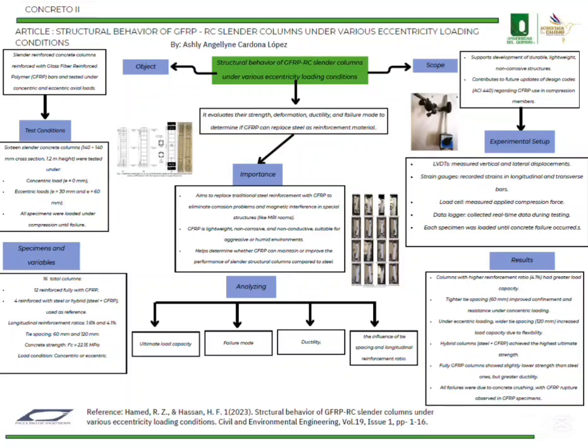GFRP is a composite material made of glass fibers embedded in a polymer matrix. It has several remarkable characteristics. It is much lighter than steel. Its density is only about one fourth or one fifth of steel's. It has a high tensile strength, sometimes even comparable or higher than steel. It is corrosion resistant, making it ideal for aggressive or marine environments. It is non-conductive and non-magnetic, which makes it suitable for electromagnetic sensitive areas. However, one limitation is a lower modulus of elasticity, meaning it deforms more under the same load compared to steel.